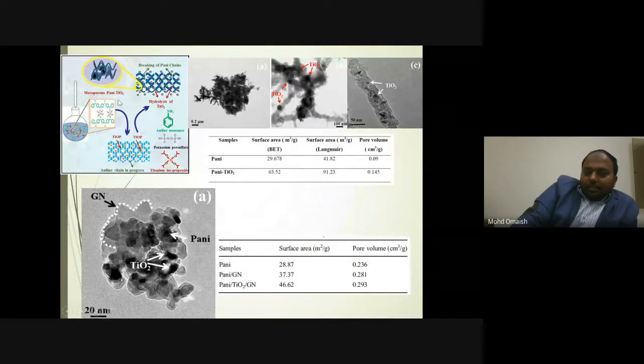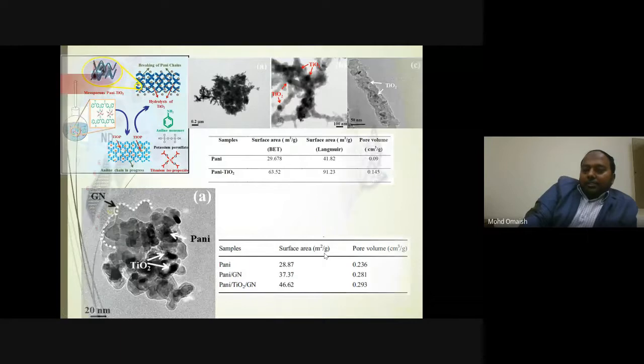Here the authors have got a very good surface area of polyaniline titanium dioxide. There was in situ synthesis of titanium dioxide as well as the polyaniline chain. The synthesis of titanium dioxide ruptured the polyaniline chain and increased its porosity, so we got a very good increase in total surface area. Also in the case of the polyaniline, titanium dioxide and graphene composite, we can see a much increased surface area of this ternary nanocomposite.